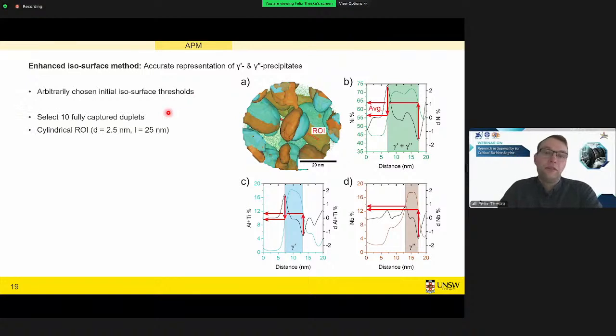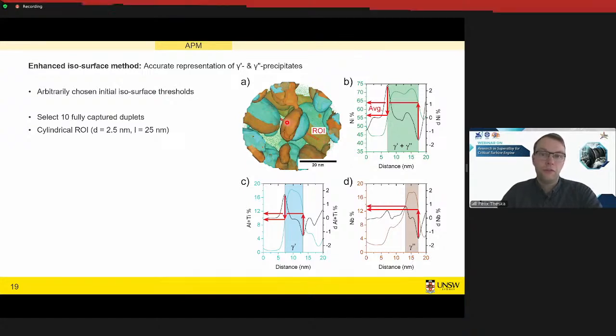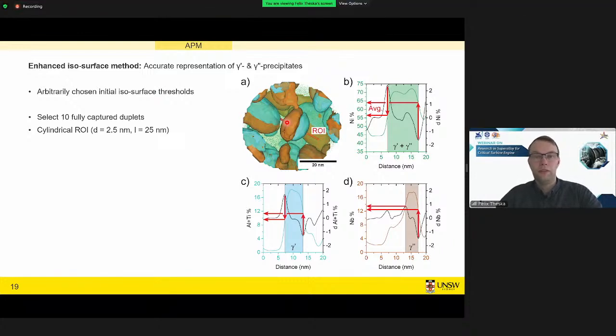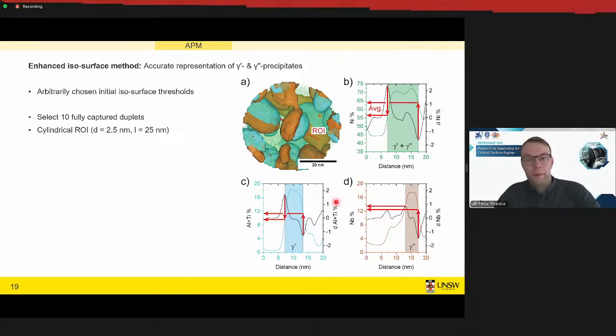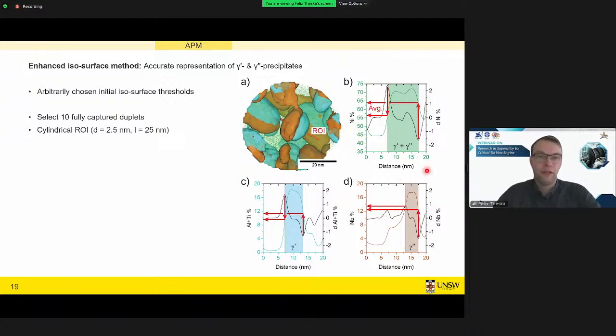What we can start with is we look at fully captured particles, such as here. We just chose a random isosurface. We just want to know where are these particles. So we plot them here, and then we put a region of interest. This is a cylinder which goes right through the duplet particle. And then we can plot a concentration profile. You see in figure B, C, and D, I've done this for nickel, aluminum plus titanium, and niobium. So the colorful graphs are the concentration profiles.